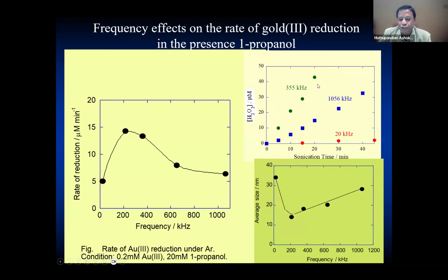And that is related to, as you can see here, this hydrogen peroxide yield as a function of sonication time for different frequencies. That tells how many primary radicals, the hydroxyl radicals and hydrogen atoms, we generate. So what you can see here is that 20 kilohertz produces a very low amount of radicals. 300 kilohertz produces a very high amount of radicals. 1 megahertz produces, again, a low amount of radicals. So the highest amount of radical production is around 200 to 400 kilohertz. So if I have a very high amount of radicals, then I produce more gold particles, which are of smaller size.